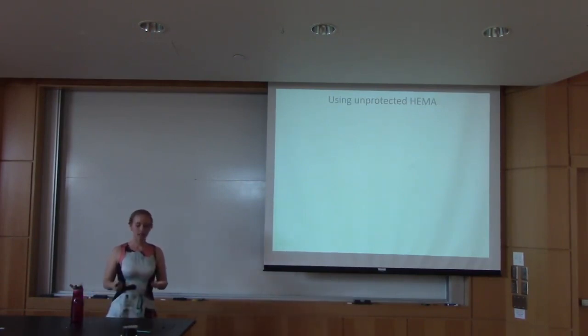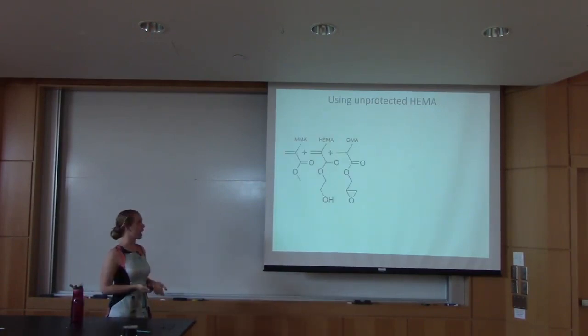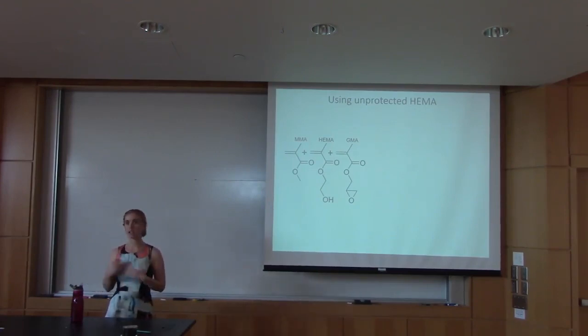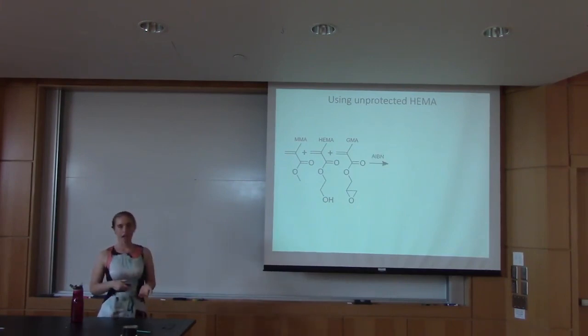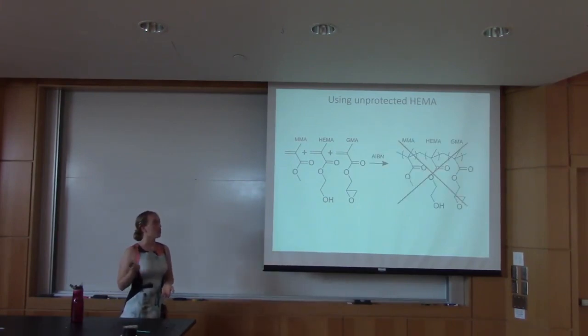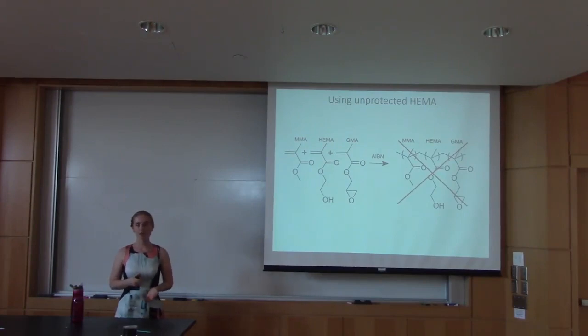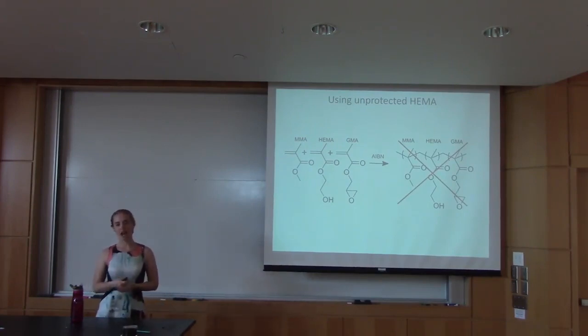And so what we did to make this molecule is we first tried by just putting together our MMA, our HEMA, our GMA, and the specific compositions that we wanted, adding our initiator, our AIBN, to start the reaction, but we didn't get that out. Instead we got this really gross gel that was impossible to work with, and we could not get the polymer out, no matter how hard we tried.